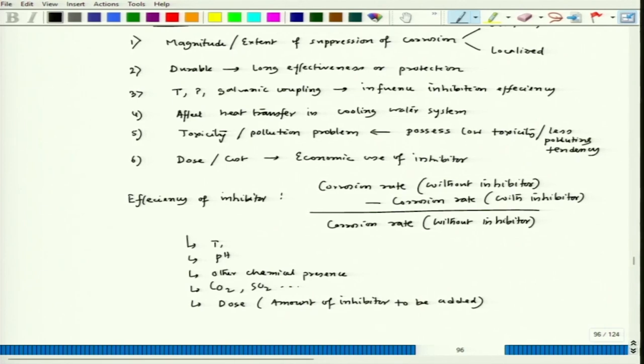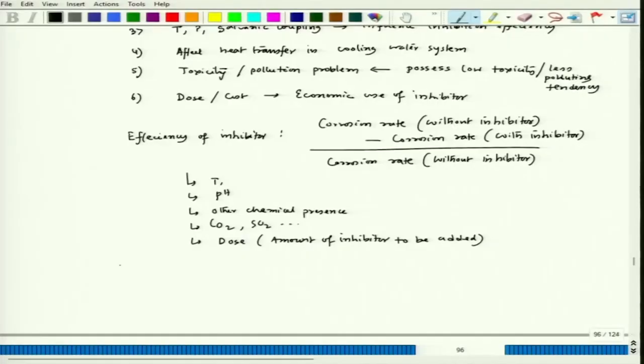For example, if we want to do experiment for a particular dose of inhibitor, let's say we want to see what will be the effect of inhibitor on the inhibition efficiency if we have low temperature as well as high temperature, let's say one temperature is 20 degree, another temperature is 50 degree, we can actually calculate by doing a simple polarization experiment. Okay, so we'll see that. Now, this corrosion rate can be calculated by simple polarization or by immersion test.